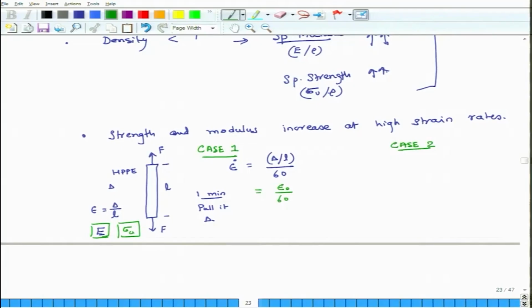In the second case, let us say time is 0.01 seconds. Okay. So, what will be the value of strain rate? Strain rate will be epsilon naught, which is delta over L, divided by 0.01. So, that is equal to 100 times epsilon naught. So, strain rate has gone up significantly, right? It has gone up how much? It has gone up by a factor of 100 times 60, right? 6,000 times. I have increased the strain rate 6,000 times.